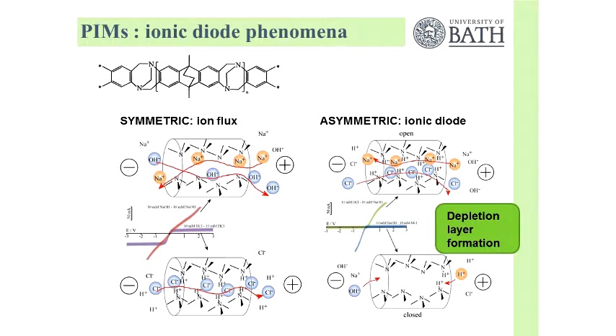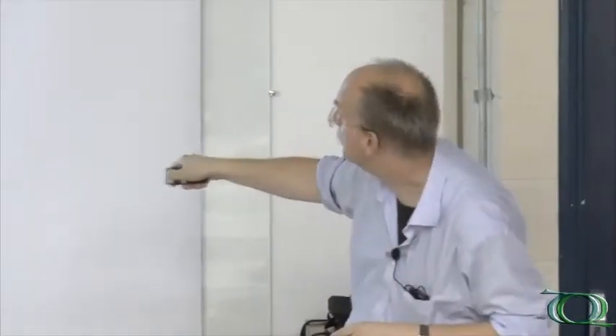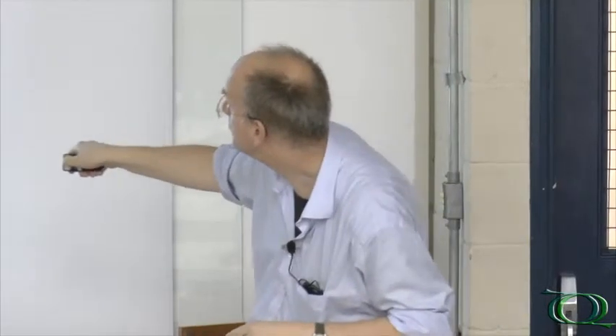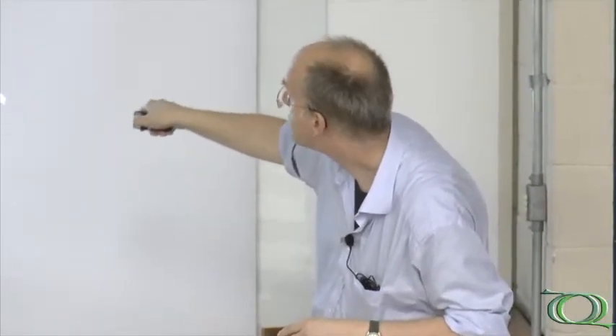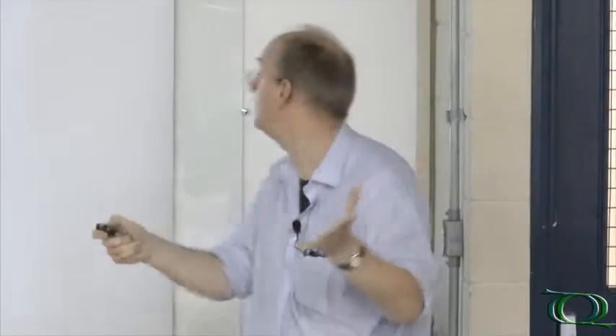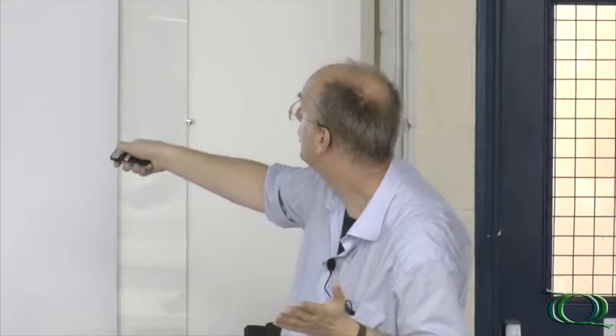This is the behavior of ion flow in this membrane. First, the symmetric case: if I put the same solution on both sides and apply a potential, I push sodium one way and hydroxide the other way. If I go to negative potential, it's the other route — the ions just flow; it's not very exciting. If I put acid on both sides, I get a bit less current. With the protonation of the polymer, only the anions move — so the chloride moves, and it's also almost symmetric.